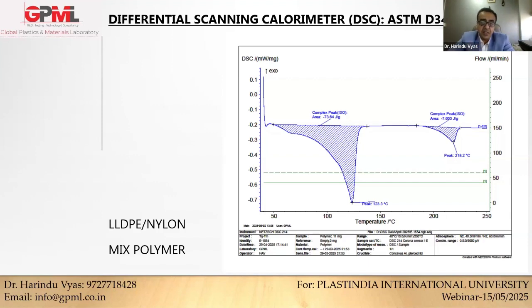Again, since it is in very small proportion, FTIR doesn't show the presence of this material because there are many other organic and inorganic materials which will hinder the spectrum of FTIR. So we won't be able to get the peaks of this material, which is at 218. But again, by our own experience, we can very easily identify that this material is nylon, which is mixed with this LLDPE in the sample.